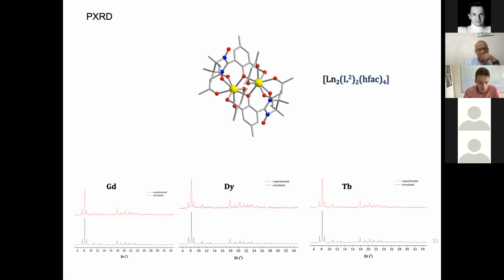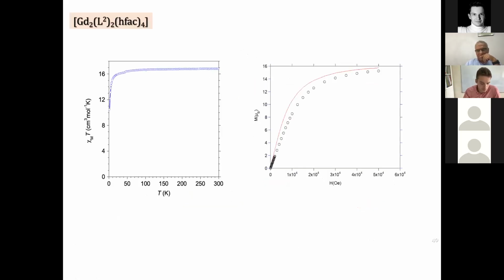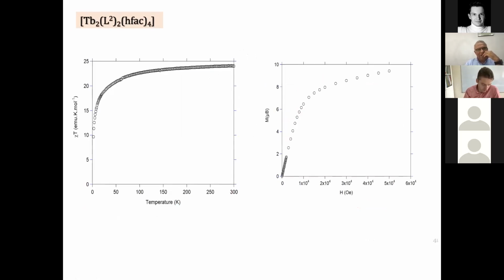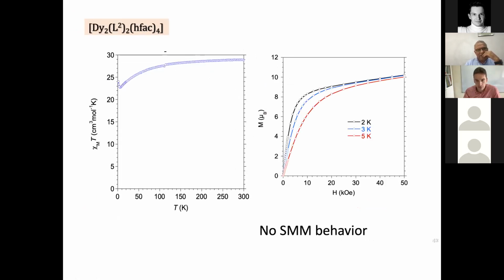So I will present only the preliminary magnetic measurements for the three compounds. So gadolinium, and in this case, we observe an overall ferromagnetic interaction, the terbium derivative and the dysprosium derivative, and our measurements indicate that unfortunately this compound is not a single molecule magnet.